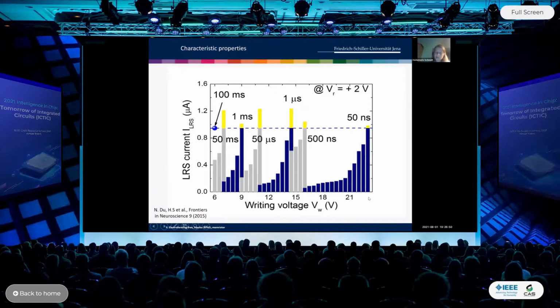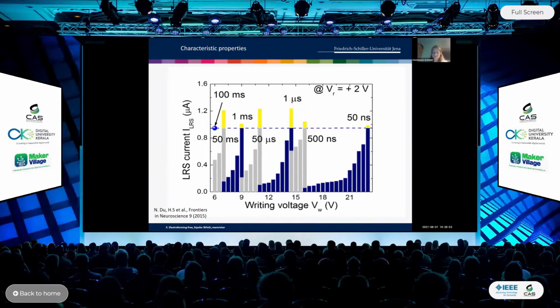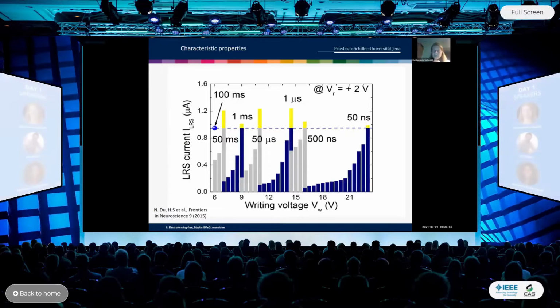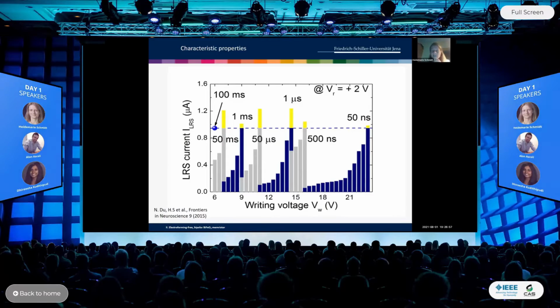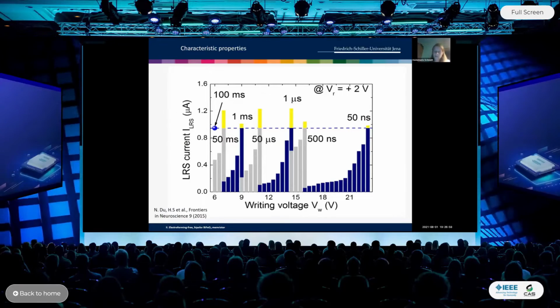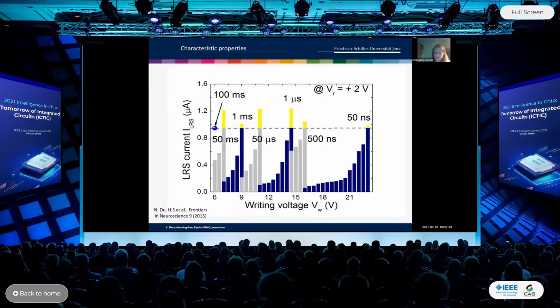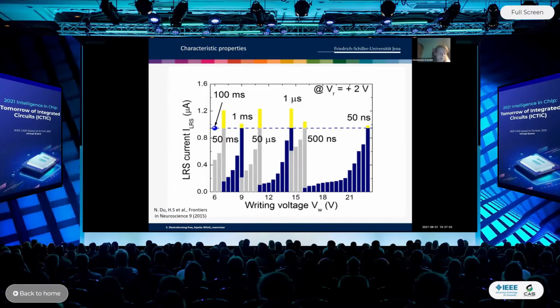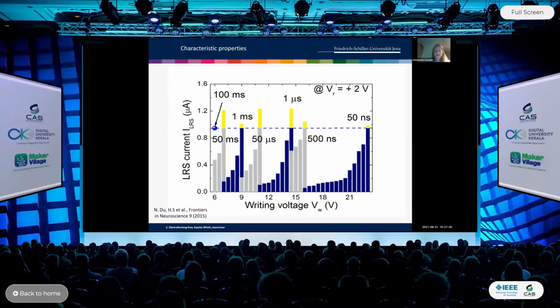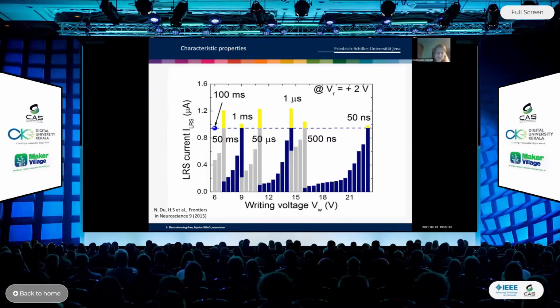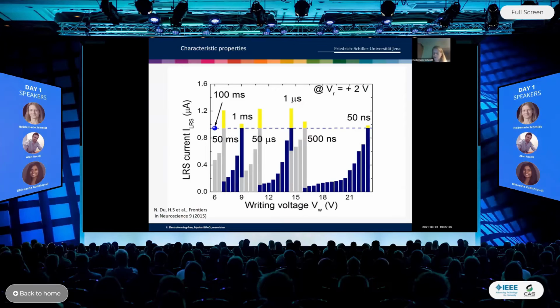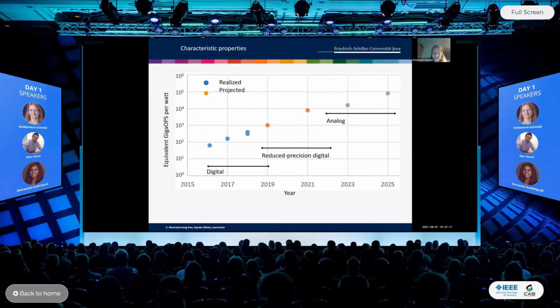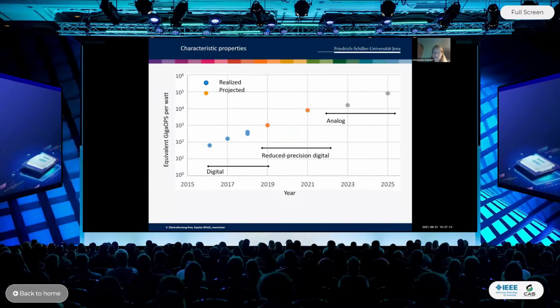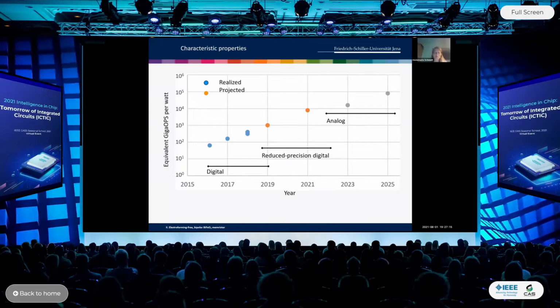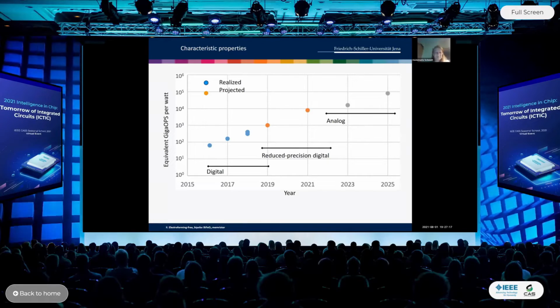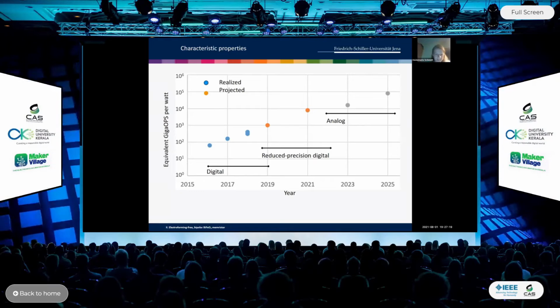This is extremely important because the system, due to this exponentially dependent drift velocity of oxygen vacancies, shows a huge dynamic range in the resistive switching. Okay, now I have described all the properties of bismuth iron oxide memristors you have to know to understand some applications in the following, and to come to the motivation for more applications.